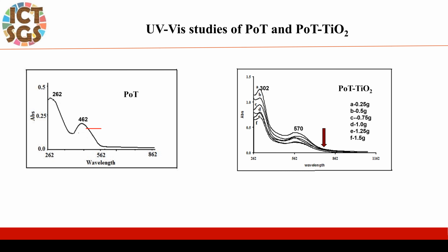With the introduction of titania into polymer matrix, the bathochromic shift was observed, and also found that the relative intensity of the peak alters with different content of titania, which shows that titania nanoparticles encapsulated by PoT chains tend to eliminate the interaction between the PoT chains, leading to dispersed polaron band.